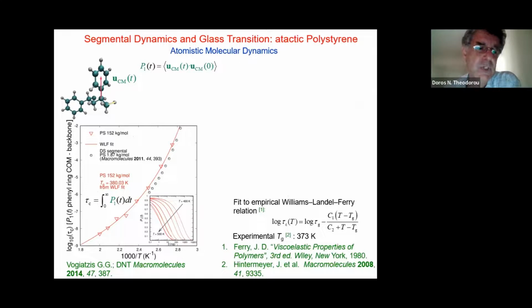However, it tends to give you shifts in the Tg because the cooling is extremely fast. When you cool with molecular dynamics, you typically cool very fast, which means that you have a too high Tg. Whereas this type of observing the relaxational process is not dependent on a cooling rate. That is its only advantage. So if one cools very, very slowly and sort of corrects for the rate of cooling, one can use the break in the volume versus temperature, enthalpy versus temperature curve, and it is not so different from the one that you get from the dynamics.